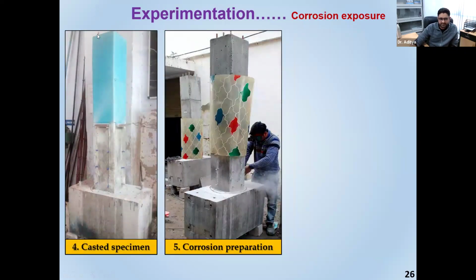And we did a GFRP wrapping over here. Again, as I said, in this region we provided closely spaced stirrups in both generation 1 and generation 2 columns. We also retrofitted it earlier. I mean, we wrapped it with the GFRP just to make sure that this region remains extra strong. This region obviously remains strong because of its size. So this region is the one where we'll notice or quantify all the failures.